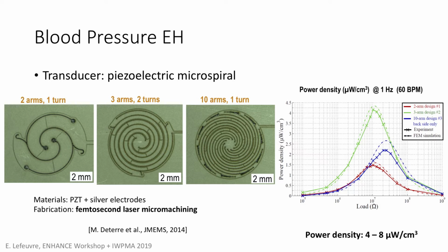So in theory we had good results, but in practice we had the results we had. That is to say, in the range of 4 to 8 microwatts per cubic centimeter, which is very, very small. It is very little because the device is much less than 1 cubic centimeter. So the real figure is in the range of nanowatts for this spiral. So it's far below the simulations.